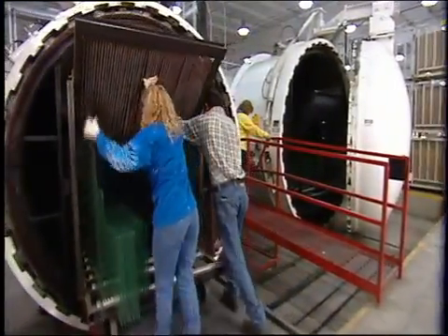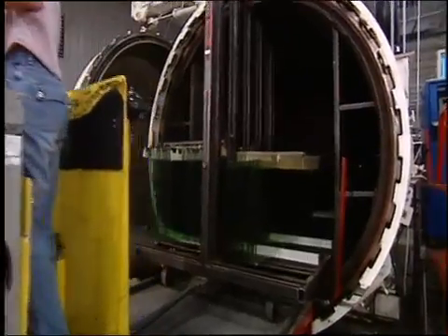In a computer controlled autoclave, the glass goes through a two to four hour process where it is heated and pressurized. This bonds the interlayer to the glass and it emerges as a clear glass sheet.